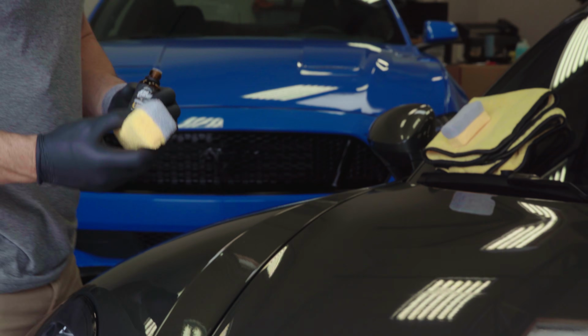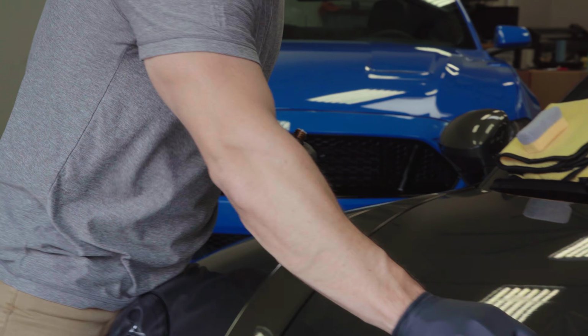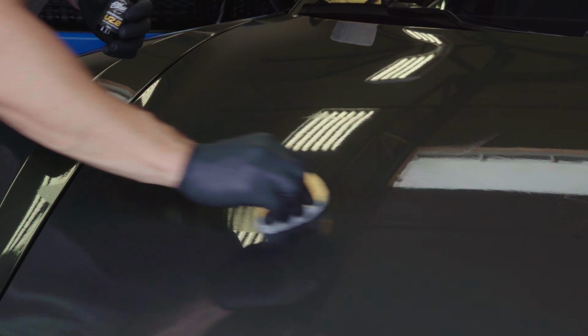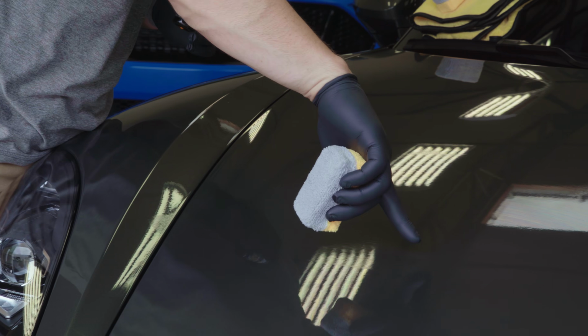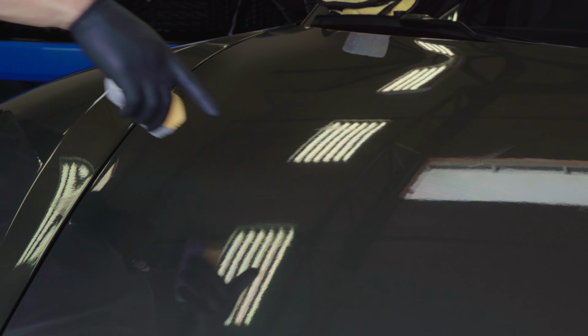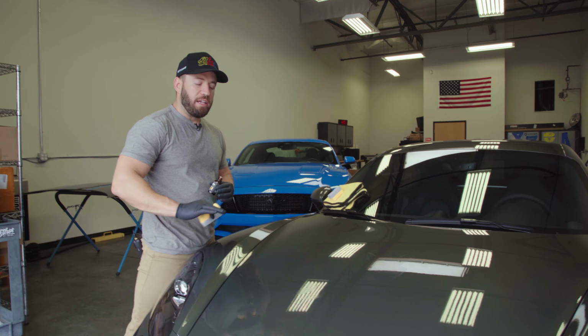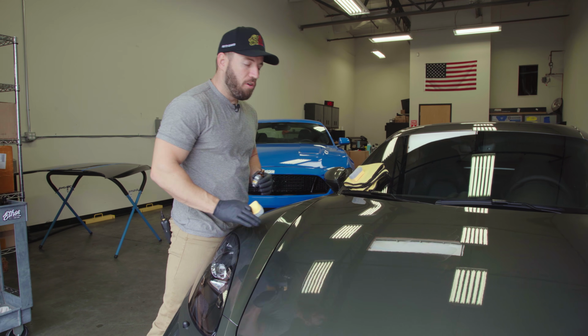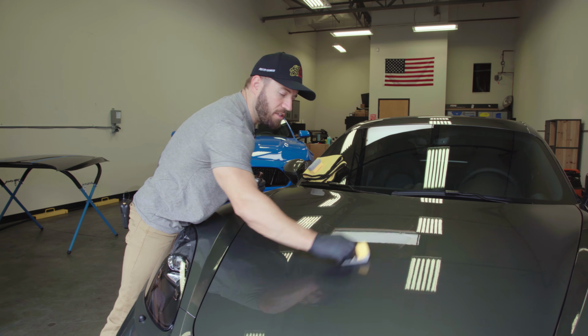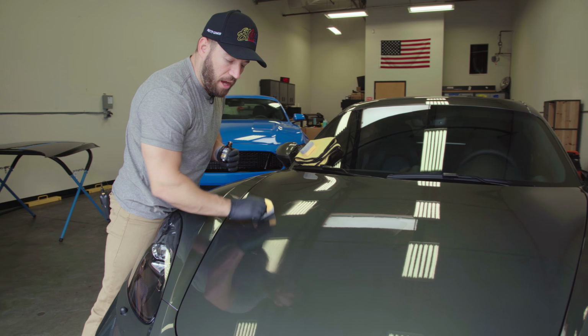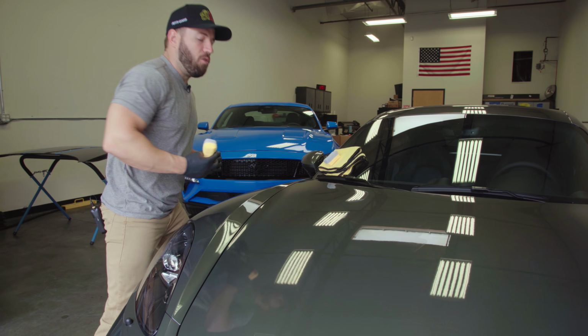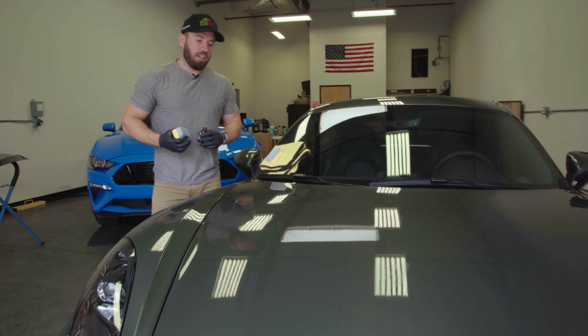Now, the one thing you don't want to do with any coating application like this is leave an area where there's a bunch of coating. Now, if I'm applying, let's say, just stop right there, and I leave a big mark of coating, what that can cause is called a high spot, which is basically a thicker layer of coating that's not able to be completely wiped off. So you just want to make sure we're using our eyes and our feel to really make sure that we're getting a nice even coating layer. That's going to give you the best results possible.